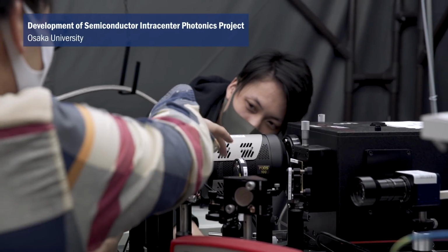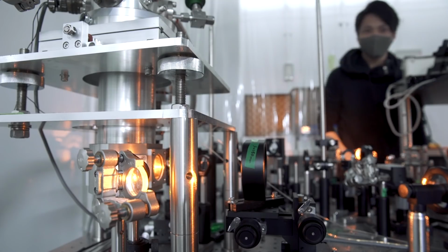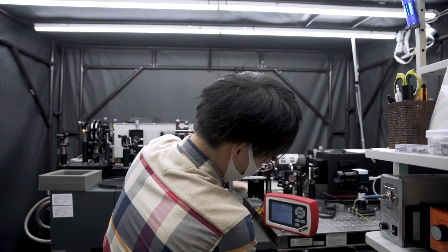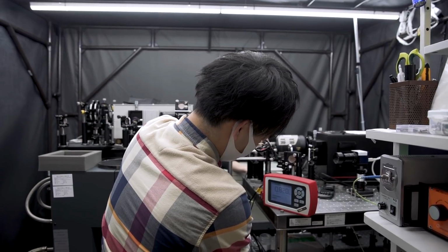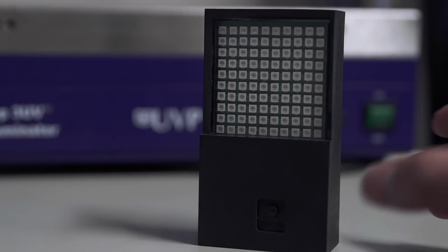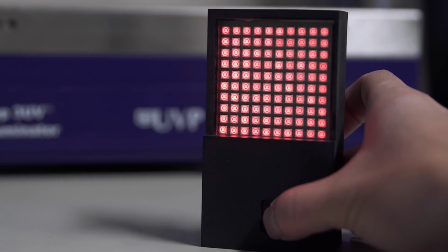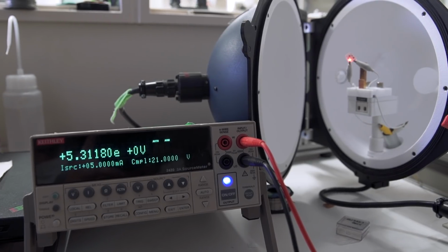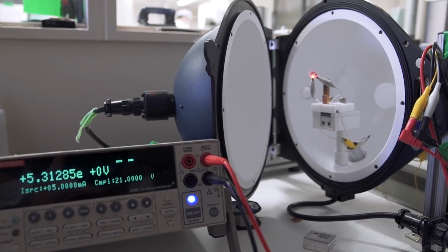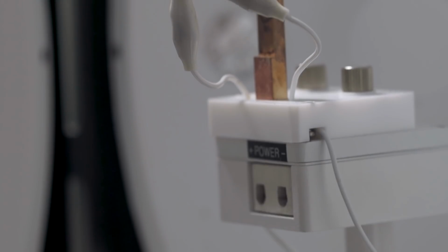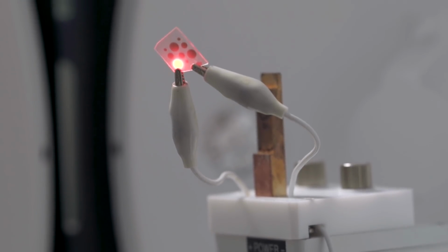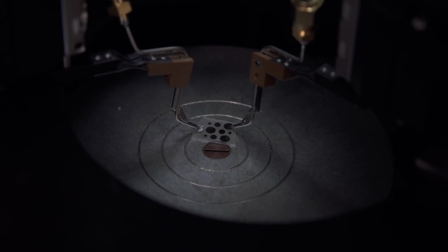The wavelength of emission is not so stable, fluctuating with the change of ambient temperature. In 2009, we invented a new type of red LEDs using europium-doped gallium nitride, which works at a very low voltage, just 3 volts. This is a big breakthrough. We demonstrated red emission and current injection.